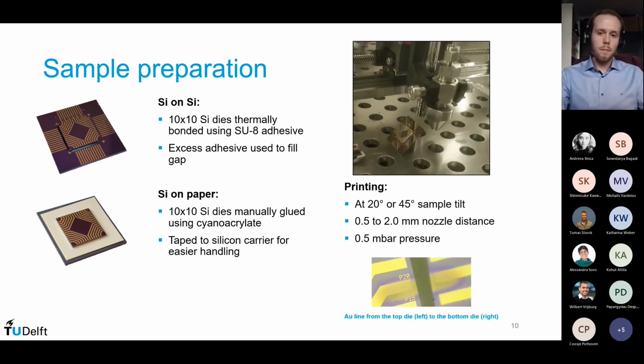So then we printed them at an angle so that we can get the nozzle to reach the side and the top surface. And we placed the nozzle as close as we possibly could, but due to geometric constraints, that was usually 1/2 to 2 millimeters. And the resulting line that you see printed here in the bottom right, this is a top view, is slightly wider than the electrodes that we printed, which is not at all an issue as long as you don't short your electrodes.